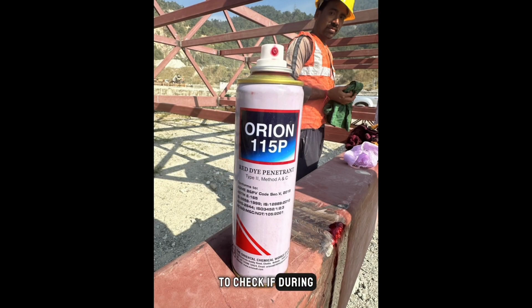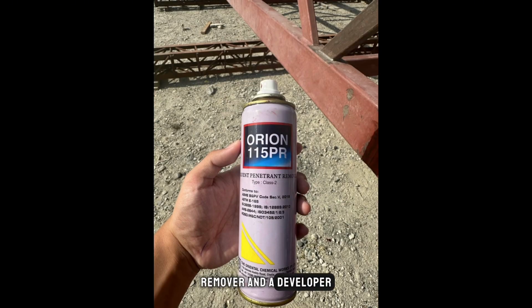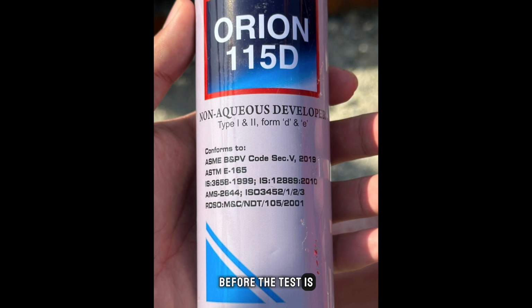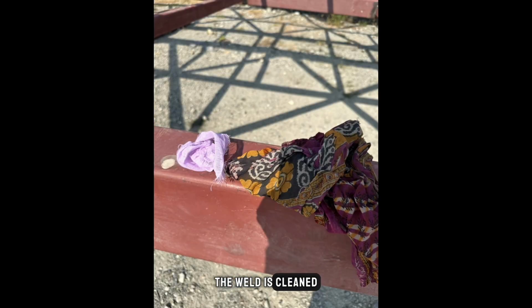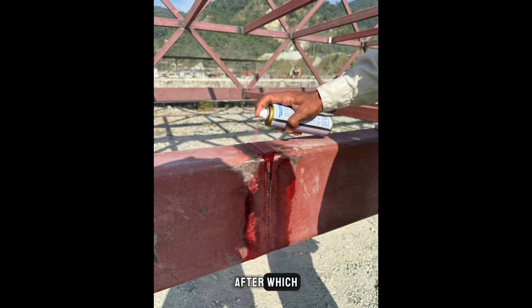To check if, during the welding, the electrode has penetrated through all the pieces, NDT is carried out. The test requires a penetrant, remover, and a developer. Before the test is carried out, the weld is cleaned and dried to remove any foreign materials, after which the penetrant is applied and left for 5 to 25 minutes.